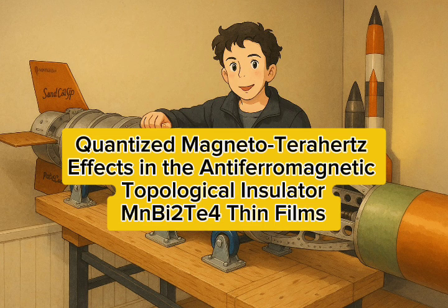You introduce a specific kind of gap, and this creates what we call a magnetic topological insulator. And here's where it gets really cool. Go on. Under the right conditions, these magnetic TIs can show something called the quantum anomalous Hall effect, or QAHE, which means you get quantized Hall conductivity. Quantized, meaning it takes on exact, specific values based on fundamental constants. Precisely. Like climbing stairs, not a ramp. The conductance locks on to multiples of a fundamental value, e²/h. It's incredibly precise and robust against defects. That's huge for potential low-loss electronics.